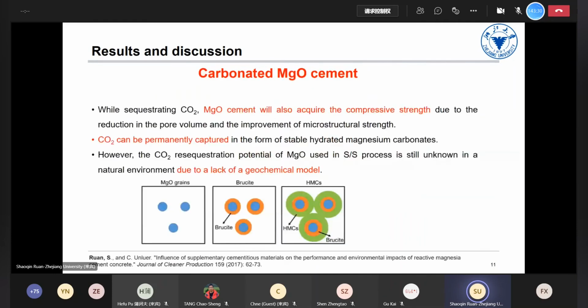First, about the carbonated MgO cement, we published a lot of papers regarding this area. As we know, the MgO cement acquires compressive strength via sequestration of carbon dioxide. So it will lead to a reduction in the pore volume and an improvement of the microstructure. The carbon dioxide can be permanently captured in the form of stable hydrated magnesium carbonate. However, the carbon dioxide sequestration potential of MgO used in SS in a natural environment is still unknown, due to the lack of a geochemical model.